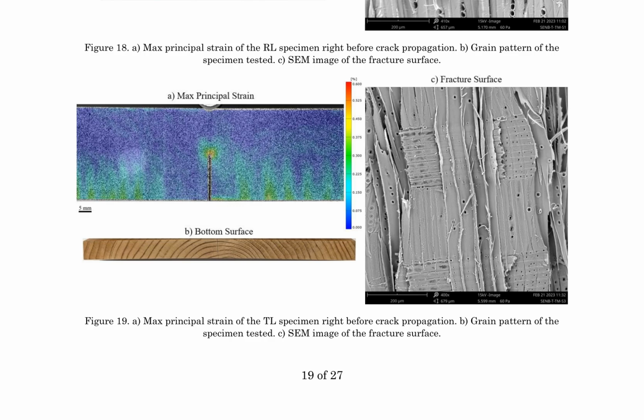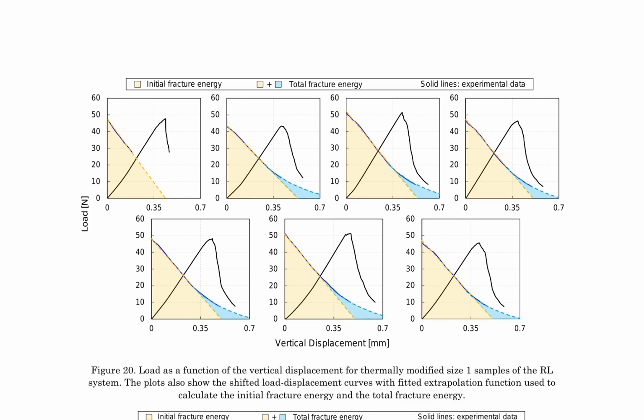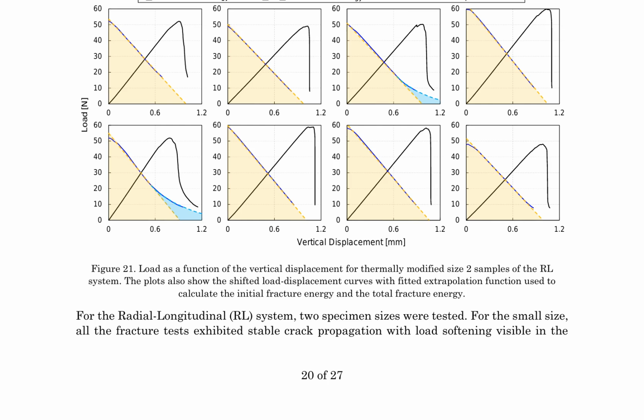The load displacement curves for thermally modified size 1 and size 2 samples of the RL system are presented. These plots display stable crack propagation with load softening visible in the experimental data. The fitted extrapolation function is used to calculate the initial fracture energy and the total fracture energy. The figures provided illustrate the grain patterns and SEM images of the fracture surfaces for both the RL and TL specimens. The strain fields, as depicted in the figures, show similar patterns for both cases, with strain concentrations at the crack tip and at the grains. However, the fracture surface appears different, reflecting the distinct damage mechanisms observed in each system.